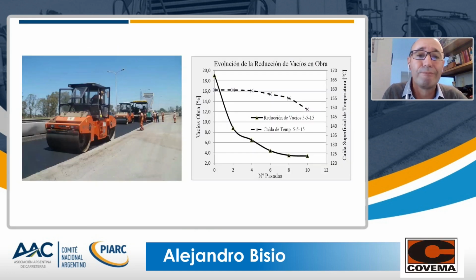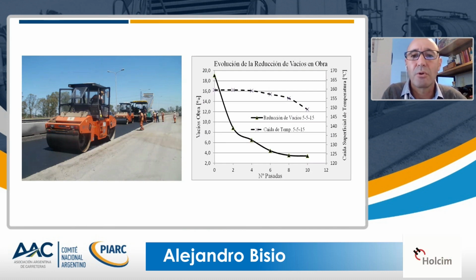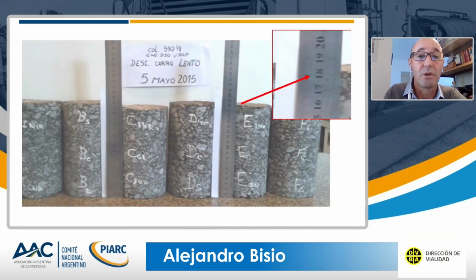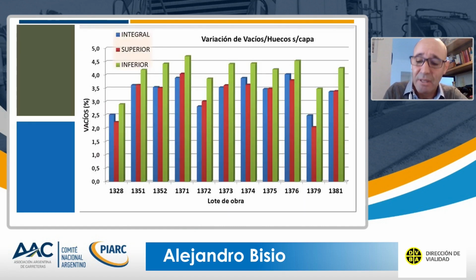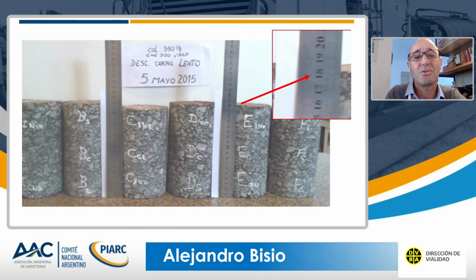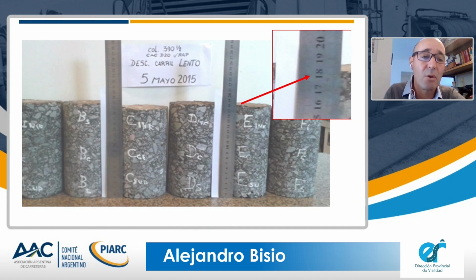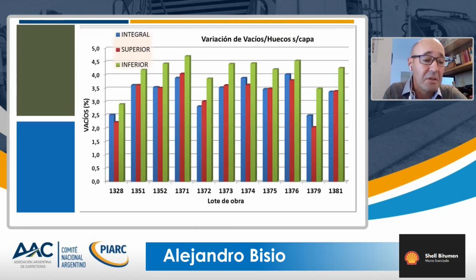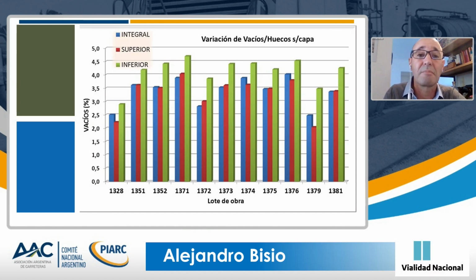And then we built the cooling curves. We checked them, especially for the compacting pattern design, in order to fix this compacting process, and this formula was used during the whole job. You can see a photo of the 18 centimeter samples, cores, and they were used to evaluate the homogeneity of these cores, and this was successfully verified, and there were no differences as to the void content in the different cores.